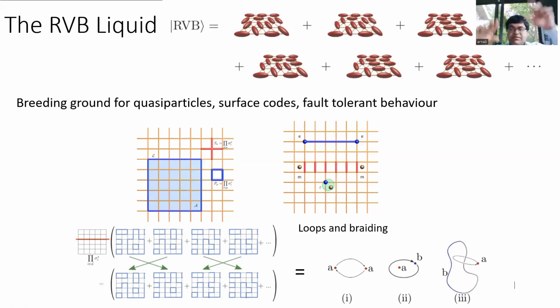And these dimers can move from one bond to the other, to the other, to the other without any cost of energy. It doesn't cost any energy to go from one dimer bond to the other, but these dimers themselves have a certain energy, which means that you have these energy modes moving around in this whole matrix of spins, which becomes the breeding ground for quasiparticles and fault-tolerant behavior, because you can, for example, do braiding. A famous spin liquid code is the toric code, where you can have spins producing two types of quasiparticles, in which you can form loops, braids, all of that. And this is possible because these are extremely pliable and extremely deformable ground states. So you can deform one quasiparticle around the other, and so on and so forth. So that's what is very possible.